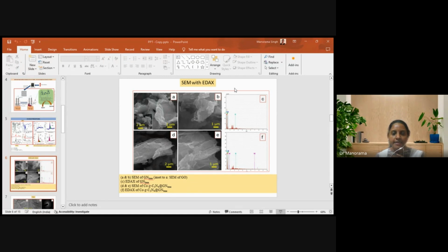In the EDX spectra, you can see here the sulfur, carbon, nitrogen, oxygen. Oxygen is there, but when we dope with the graphite carbon nitride, cobalt doped graphite carbon nitride, again all the elements are present which can be detected in the EDX spectra. Further, we have done with the TEM here.